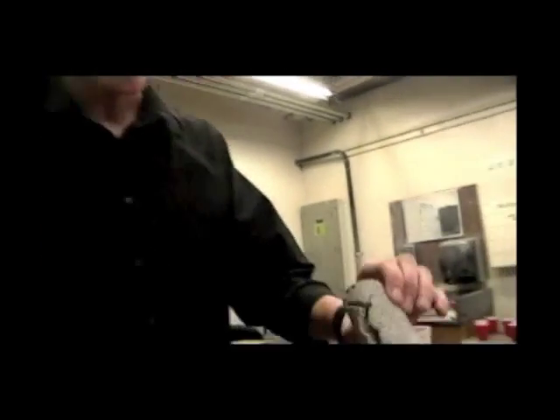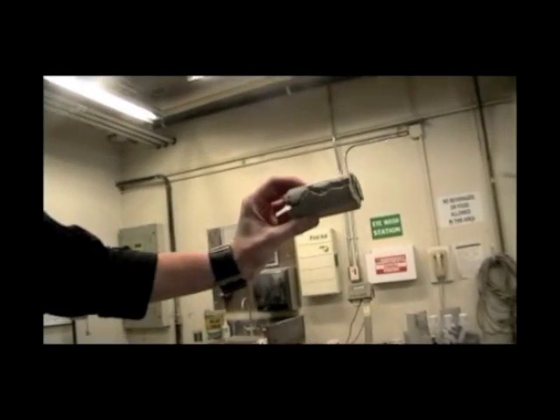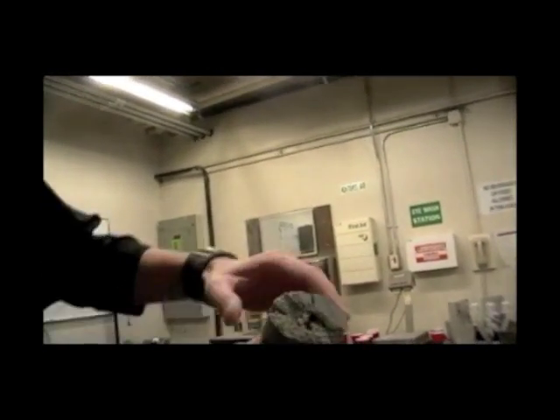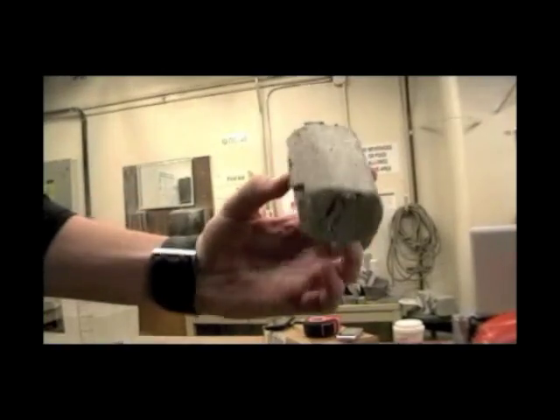As you can see with this sample, this went through a split tensile test. The PVA fibers and the latex within allow this to stay together even though it's been crushed and has failed.